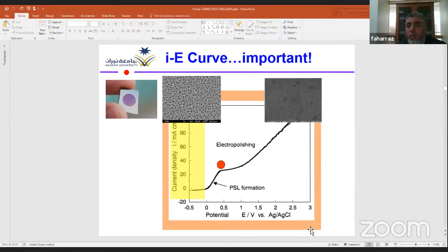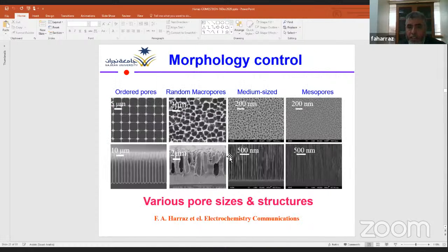For people who are interested in porous silicon technology, you have to conduct what is called a current potential curve before performing the anodization. The reason is to determine the critical current, beyond which electropolishing starts to take place on silicon. So you have to determine this critical current to avoid working beyond it and not enter the electropolishing regime. These are some nice pictures of porous silicon with various pore sizes and structures: ordered pores, random macropores, medium-sized pores, and mesopores.